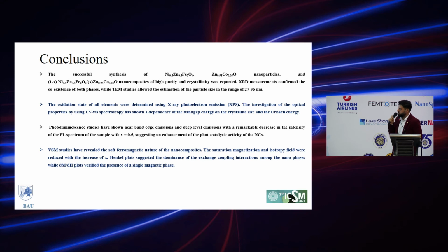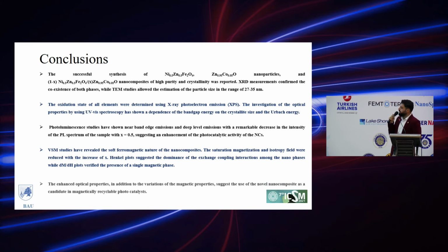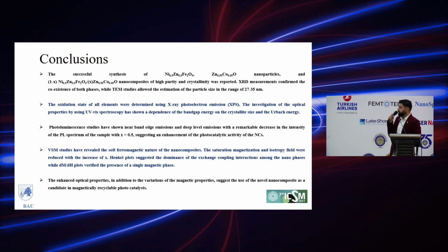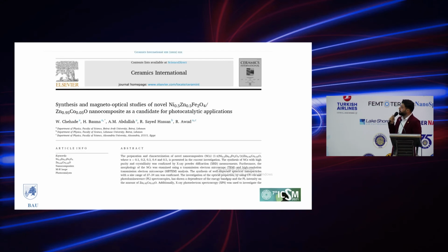Henkel plots suggested the dominance of exchange coupling interactions among these nanophases, and the dM/dH plots verified the presence of a single magnetic phase. Finally, these enhanced optical properties, in addition to the variations of the magnetic properties, suggest the use of the novel nanocomposite as a candidate in magnetically recyclable photocatalysts. This work was recently published in Ceramics International.